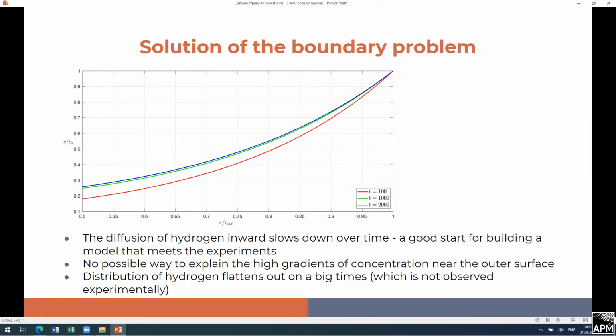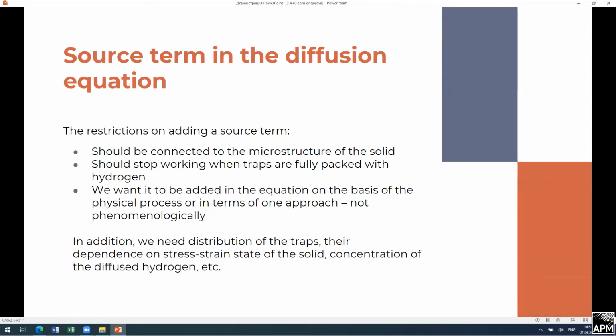But the problem is that we cannot describe the high gradients and this boundary layer which we observed experimentally. And the second problem is that with time the distribution of hydrogen flattens. So we cannot say that we have a boundary layer, which experimentally is not propagating inside the material. So the idea was to add a source term in the diffusion equation. We want to connect it with the microstructure of the solid, so-called traps in the theory, which can be microvoids or microfractures and so on. So we want these traps to work as a source term and stop working when they are fully packed with the hydrogen. And we want to add this source term based on some physical process, but not phenomenologically.